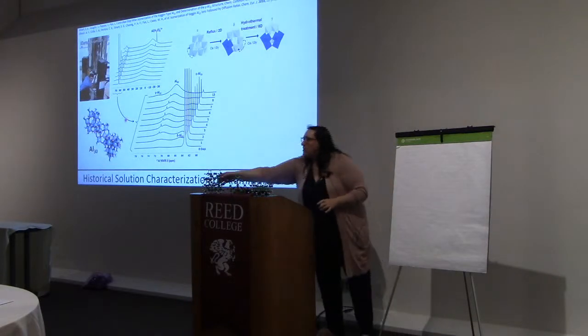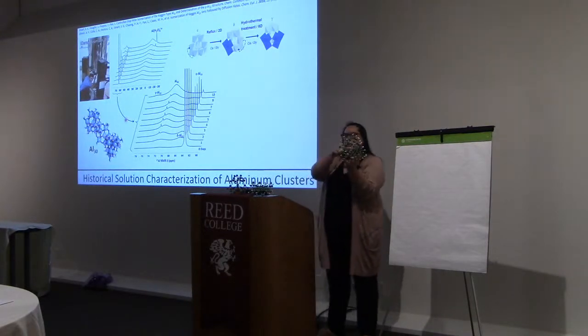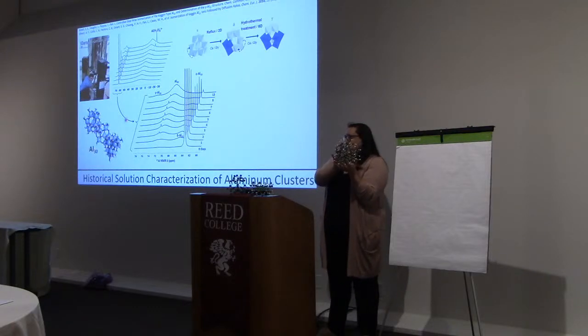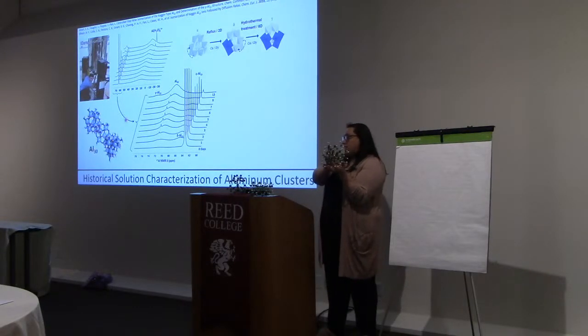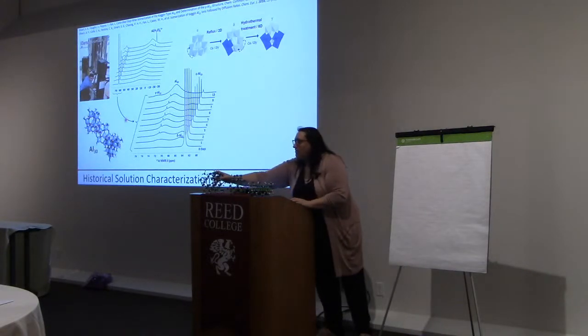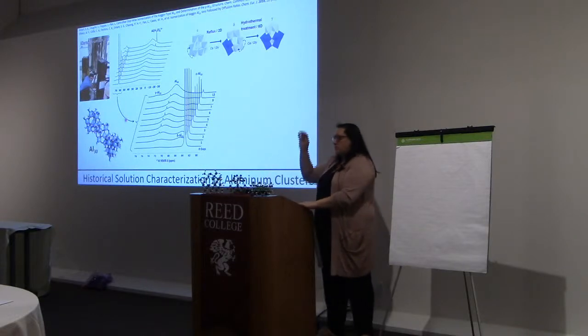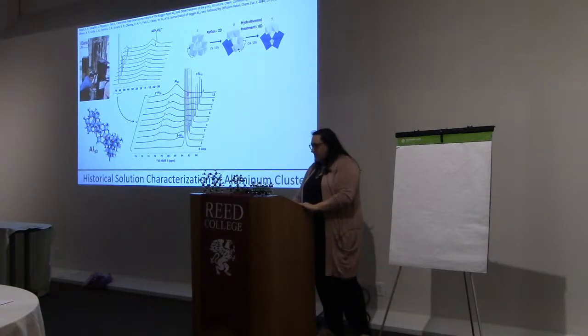Now there's only one tetrahedral aluminum in this cluster. 12 of them are octahedral. But that one very symmetric aluminum in the middle corresponds to this signal here. And as we heat that, that signal disappears.